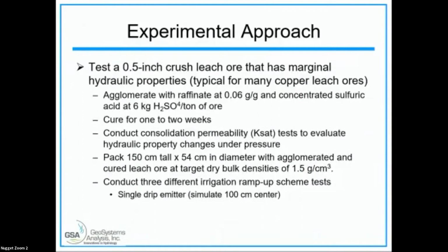So the experimental approach we took on this is we got about a ton of leach ore, and big shout out to BHP and Freeport that provided the ore for this experiment. We wanted to have a leach ore that had marginal hydraulic properties, and I'll talk about what that means in a minute. In other words, we know it has the potential for some permeability issues. The ore was agglomerated with raffinate at 0.06 grams per gram, 6%, and concentrated sulfuric acid at 6 kilograms of sulfuric acid per ton of ore. And this is the recipe that the mine uses. Cured for 1 to 2 weeks.